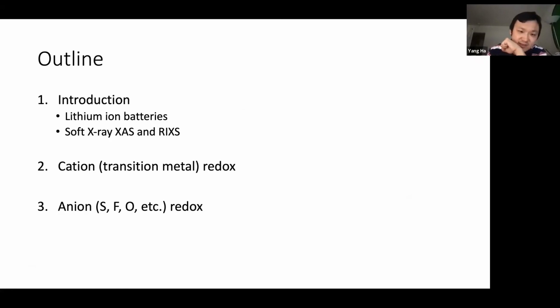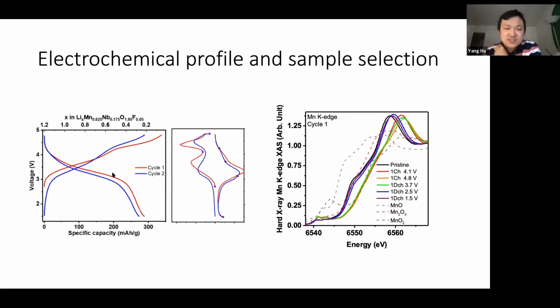So part 2, I'm going to talk about some cation redox monitoring. First, this is the electrochemical profile, measured by our collaborators or the sample providers. The x-axis is the capacity, or you can think of it as the amount of lithium pumped in and out. The y-axis is the voltage. The red would be the first cycle of charge, then the first cycle discharge, then the second cycle charge and discharge, and so on. We are particularly interested when there's a dramatic change in the slope, because that usually indicates a phase change. So we can take the derivatives and find these key points for the samples, isolate them, and measure them.